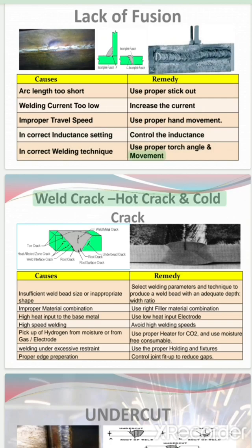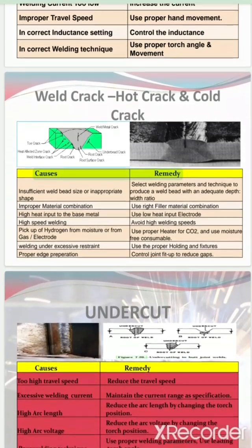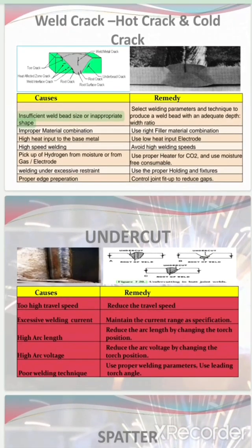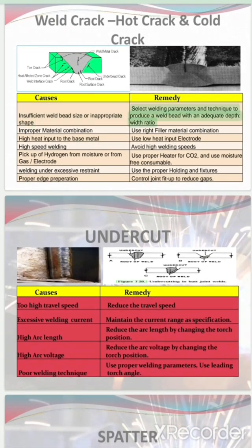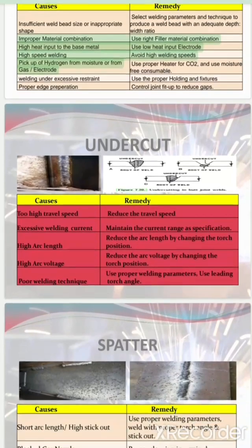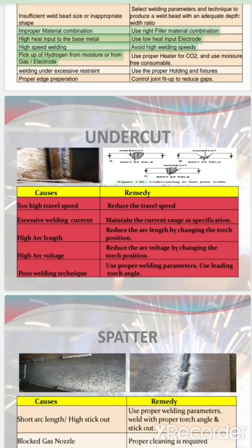Weld crack: hot crack and cold crack. Causes and remedy: insufficient weld bead size or inappropriate shape. Select welding parameters and technique to produce a weld bead with an adequate depth-to-width ratio. Improper material combination, use the right filler material combination. High heat input to the base metal, use low heat input. Electrode high speed welding, avoid high welding speeds.